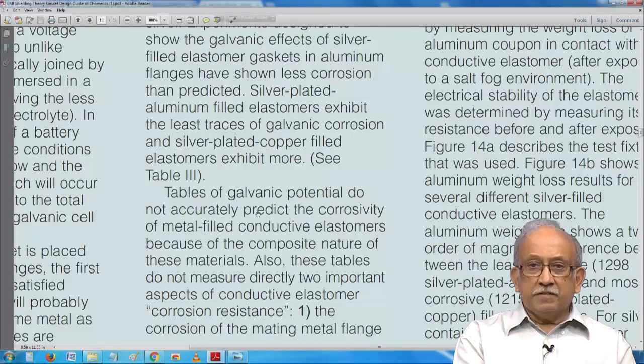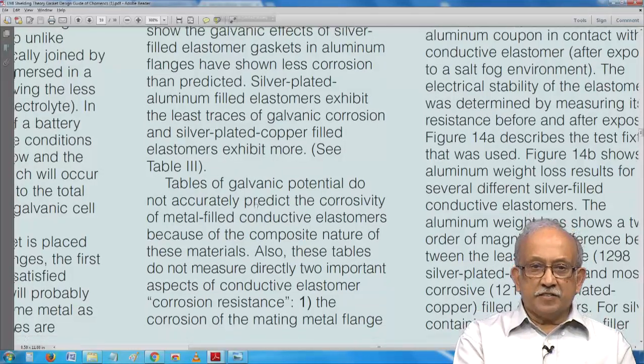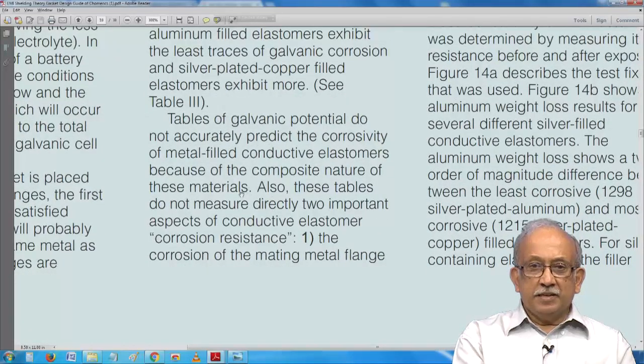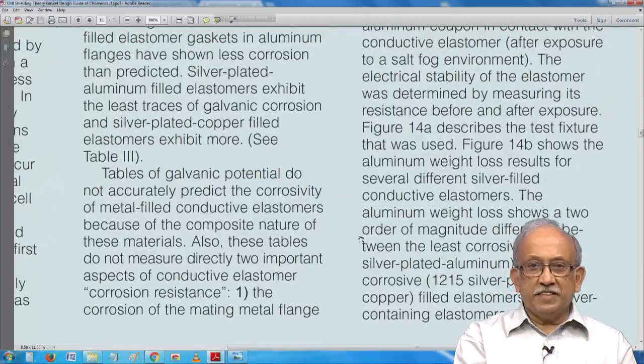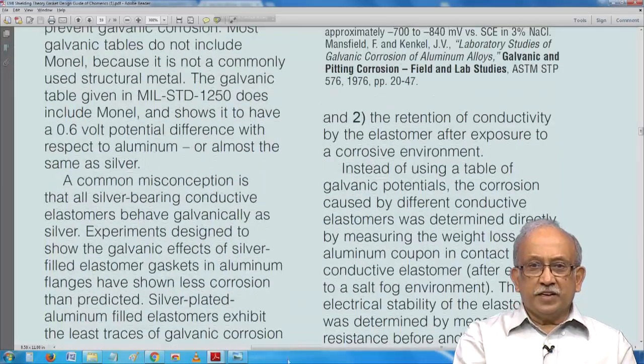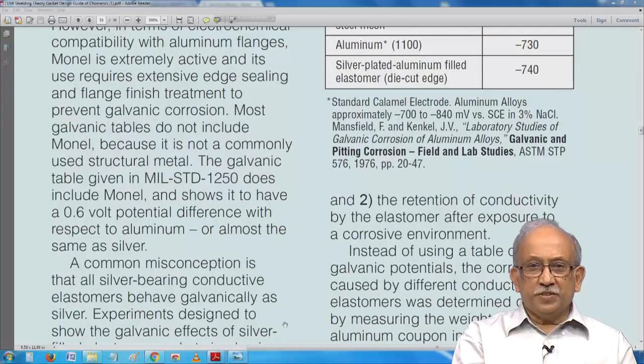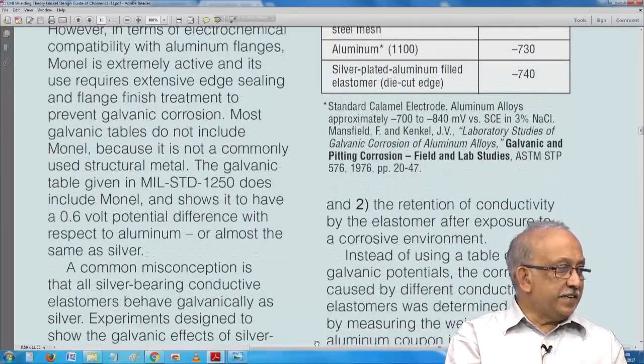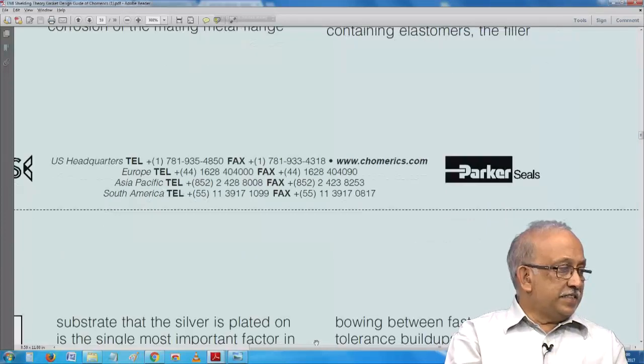But in spite of it, a caution has been given here. Tables of galvanic potential do not accurately predict the corrosivity of the metal filled conductive elastomers because of the composite nature of these materials. These tables do not measure directly two important aspects: corrosion resistance, the corrosion of the mating metal flange, and so on. If you go down, you will see that a huge amount of data is generated. Allow me to move on to the next slide.